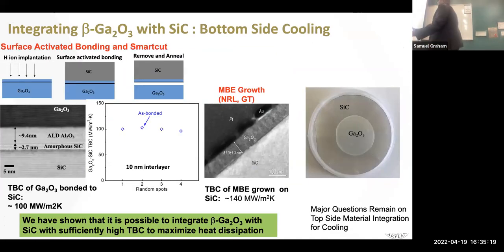And again, the same thing holds true, that I can do this wafer scale. We've also done some growth with the Naval Research Laboratory where we can grow these together. Instead of 100, this is slightly higher, 140 megawatts per meter squared K. So just slightly higher if you do the growth. But again, with the throughput of purchasing silicon carbide wafers and gallium oxide wafers, I can just bond these